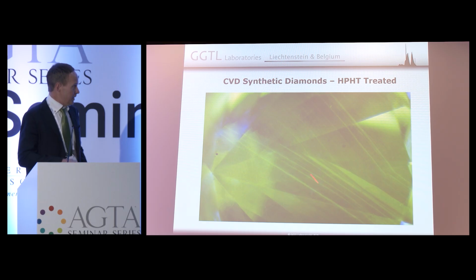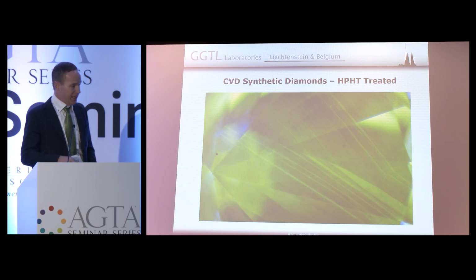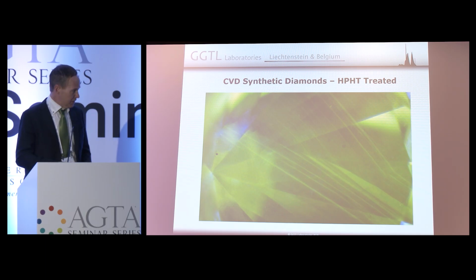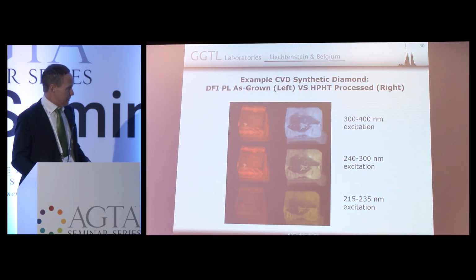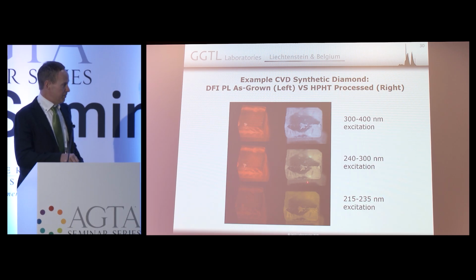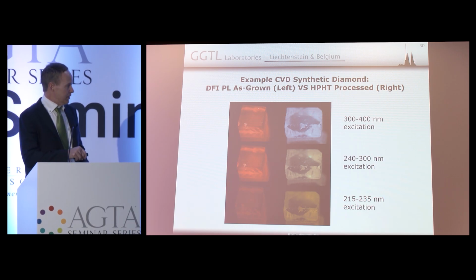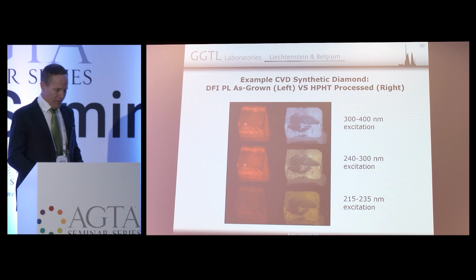So this is an HPHT-treated stone under deep UV excitation. You can see this yellowish green fluorescence, and you see the growth lamellae just like in the other example. This is a deep UV image. Now, if you look at a stone that we treated before, this was before treatment, this was after treatment, at different excitations. Before treatment, as I said, it fluoresces orange. After treatment, it fluoresces rather bluish under the longer wavelength, and it goes towards green under the shorter wavelength. So this is very typical for CVD material after HPHT treatment.